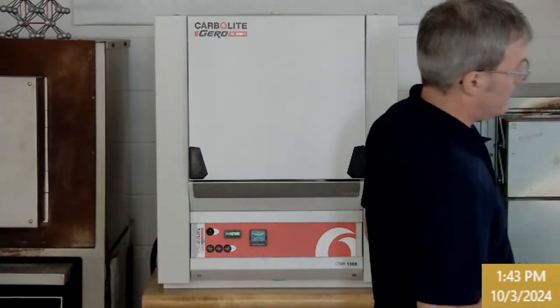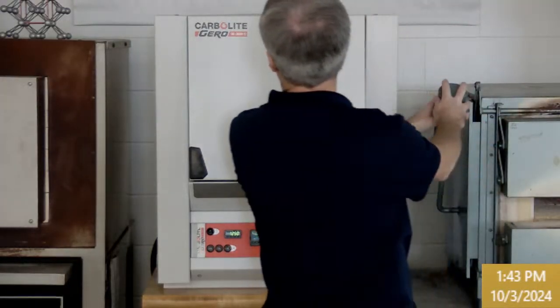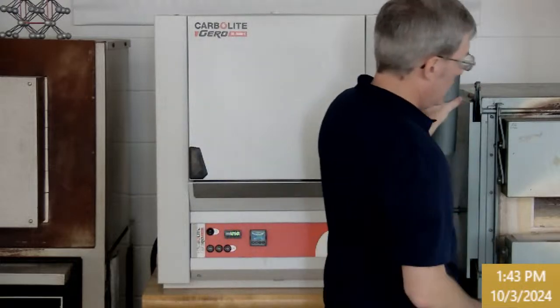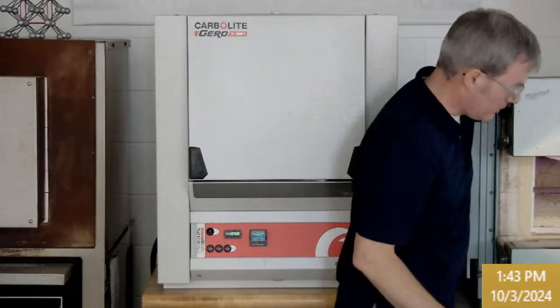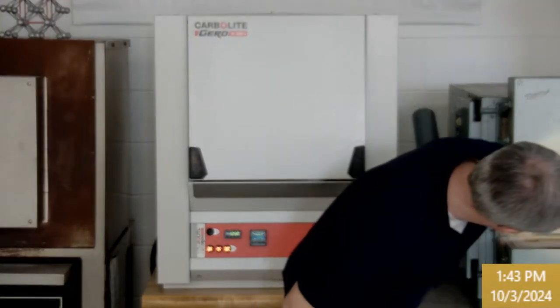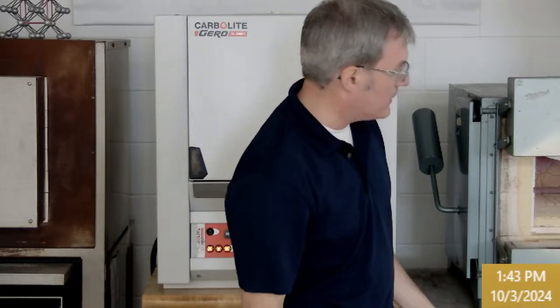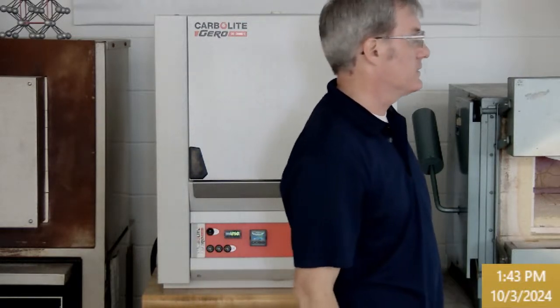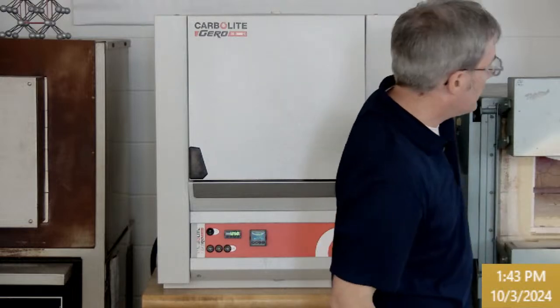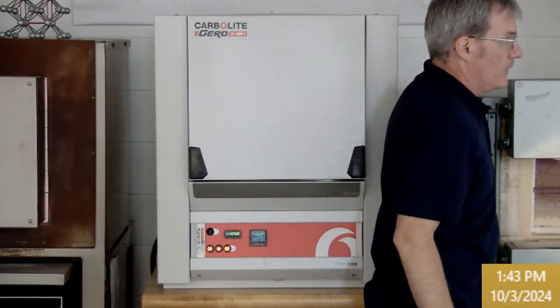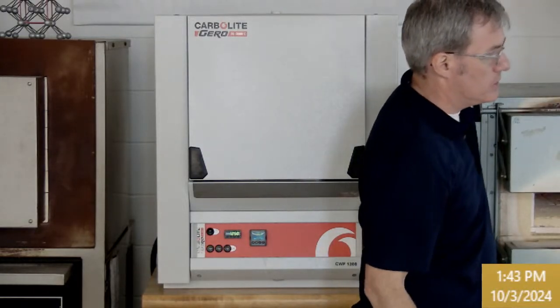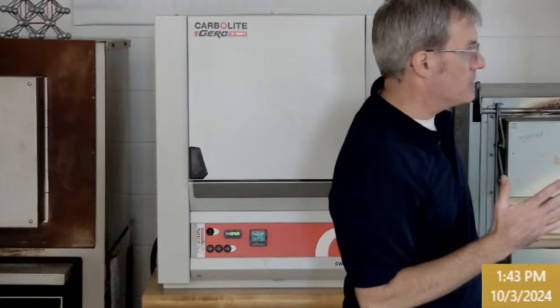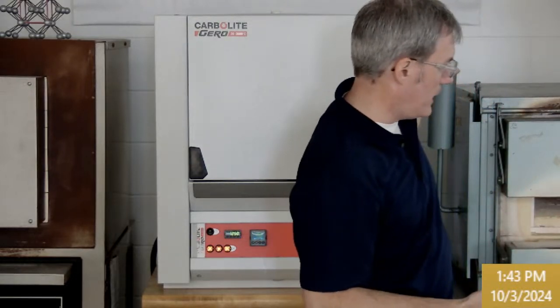Another issue with lithium is that it's so small. If you look at that 6.9 grams per mole, it actually starts to evaporate, and it fluxed the inside walls of my furnace and made them weaker. And so I haven't been putting lithium flux in the newer furnace as a result, because lithium is just kind of destructive at this temperature. But that's there for you to answer the questions. And if I shifted my temperature range lower, I could make lithium glass more manageable.